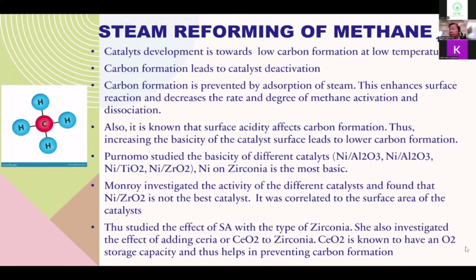These are nickel on alumina, nickel on silica, nickel on titania, and nickel on zirconia. This research was correlated to the activity test conducted by also our researcher, Mr. Monroy, in 2006. However, the best catalyst was not nickel on zirconia.